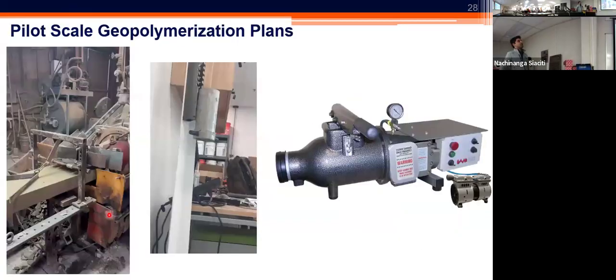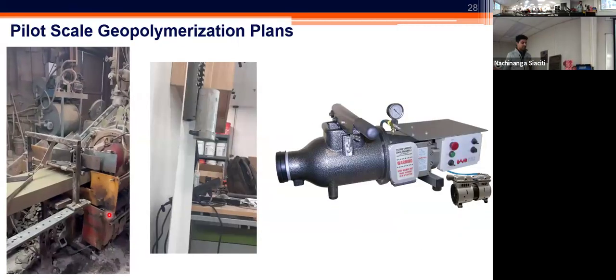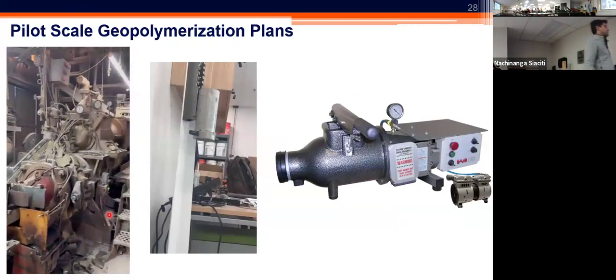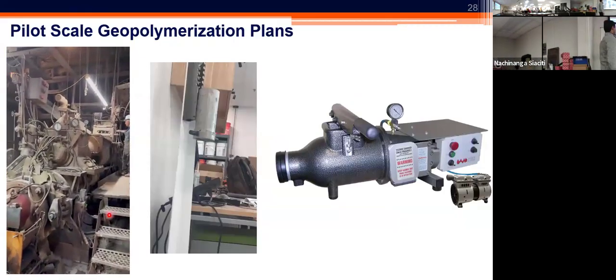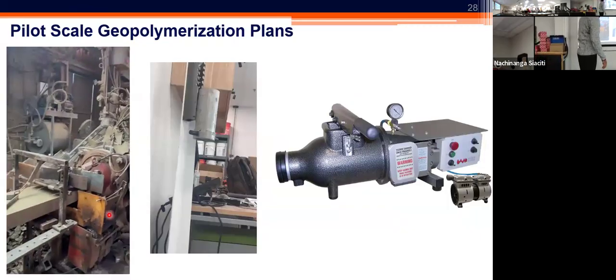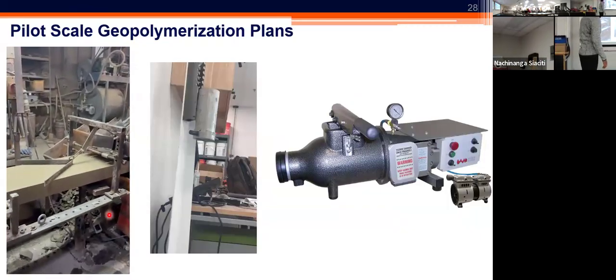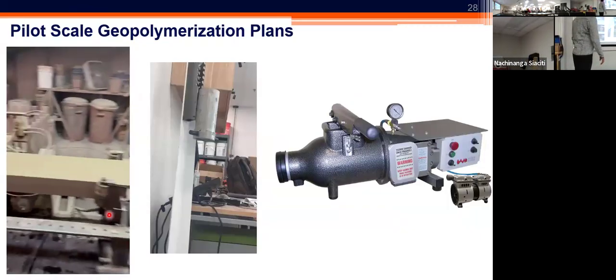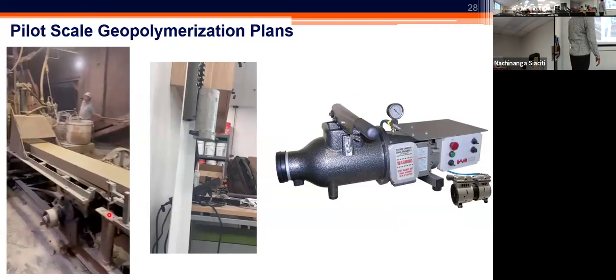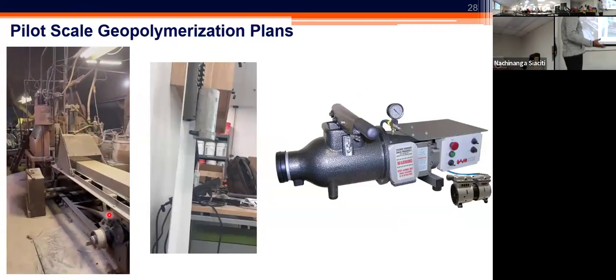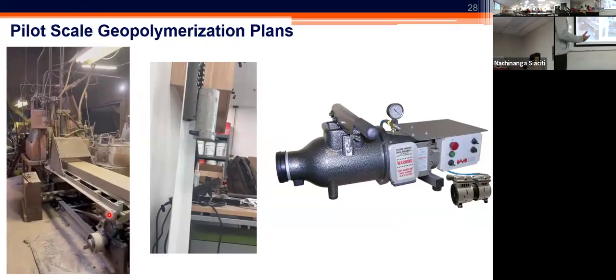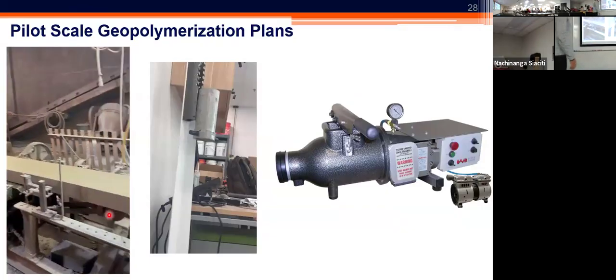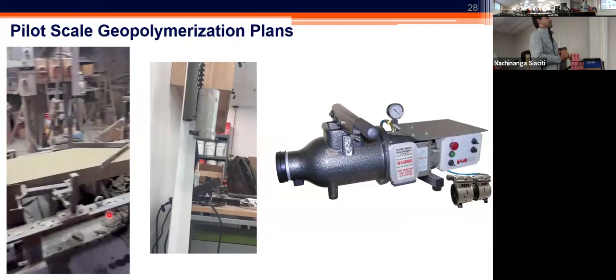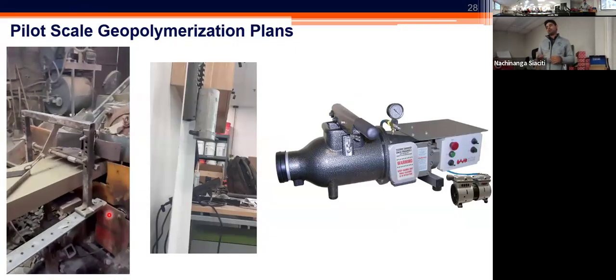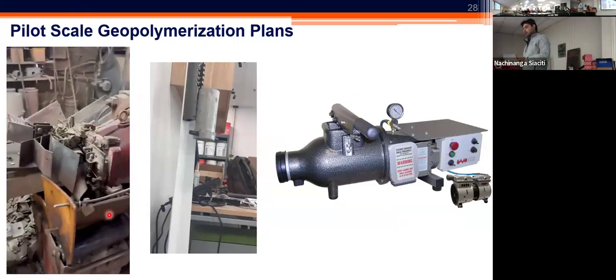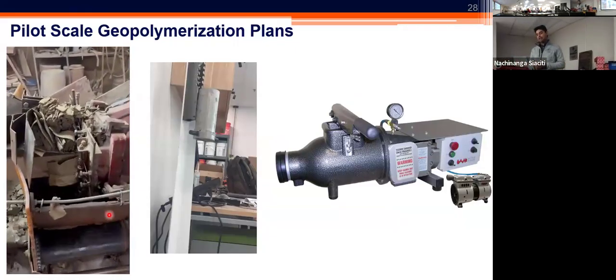So if you look at the industry and the practices, you realize that for the brick to be made at the larger scale, you need to have a big extruder where you can extrude the material at the large capacity. We are looking at thousands and tens of thousands of bricks to be made on a daily basis. So obviously the process that we have at the laboratory is not really scalable, but we are looking into some alternative solutions where we can essentially develop an extrusion-based technique for the production of these bricks at the later time.